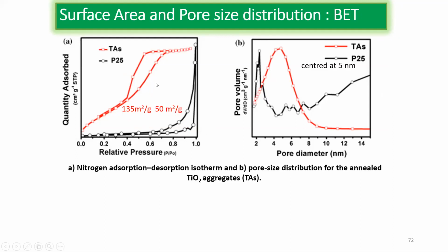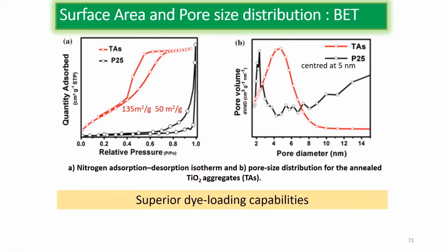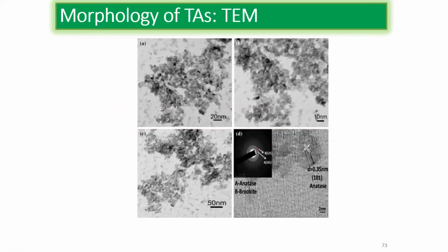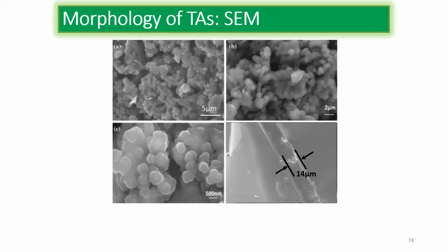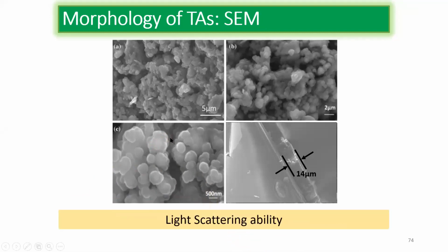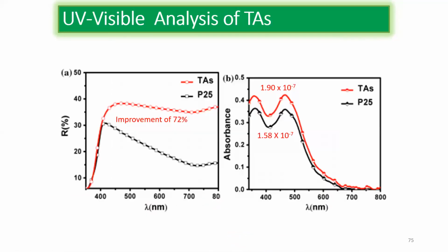So I found that this material is loosely packed and also has good porosity, with the pore size centered at around 5 nanometers. So I solved the problem of dye loading. Then in TEM analysis, I got very small crystallites, although the aggregates are of bigger size, with crystallites of around 10 nanometer. And the particle size is approximately around 300 nanometer. Although the crystallite is small, the particle size is very high. So overall, I can get better dye loading.